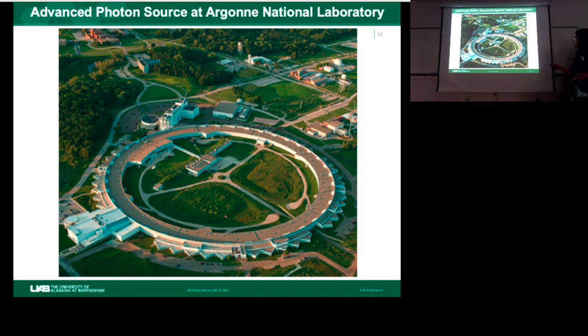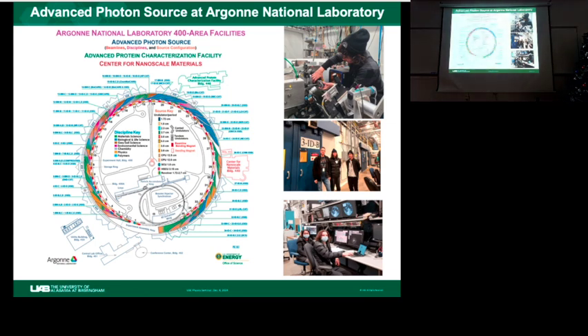So the synchrotron X-ray, in this case the Advanced Photon Source, is well known for hard X-ray applications. The typical energy scale is higher, on the level of tens of kiloelectron volts, and in that range diamond absorption is almost negligible. You don't have to concern too much. That's also a reason synchrotron facilities like APS put a pretty large focus on high pressure research. In fact, there are at least 3 or 4 sectors that dedicated some of the beamlines for high pressure research.